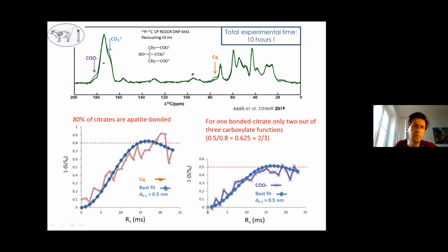You also see proximities coming from carbonates, but these are carbonates from the hydroxyapatite acting as substitute ions. So with this experiment, we're able to see that only 80% of the citrate units are actually bonded to the mineral.